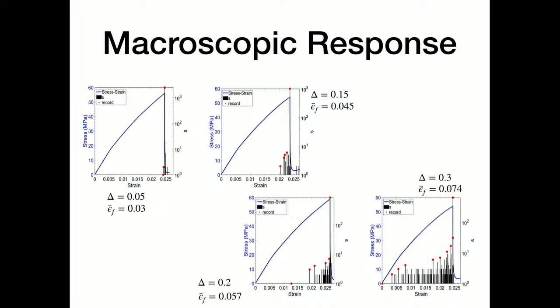So initially we do a parametric study to see, because our distribution is now a normal distribution, what is the effect of disorder. And we see that, so this is delta small now is low disorder, delta high is high disorder. We see very similar to what we had seen earlier, that for low disorder you see nothing happening, and then there is large events and few records. As you increase the disorder, more number of events and progression towards fracture is again still in an acceleration mode. But as you go further down, you can see that the first record occurs fast, and then the next records become slower, then there is a long gap, and then there is acceleration.